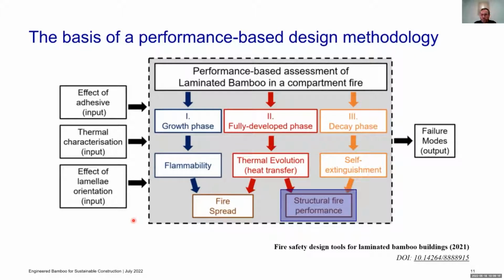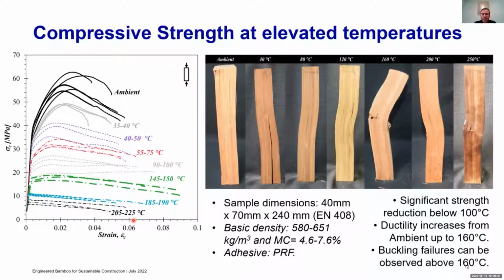So just moving into those tests that I did to understand the structural fire performance, I started doing testing on the compressive strength of laminated bamboo. What you can see here is a stress strain curve. The black line is the typical behavior of laminated bamboo. I ended up using the European standard for testing timber, like engineered timber products. So the columns or the specimens that I used were slightly larger.